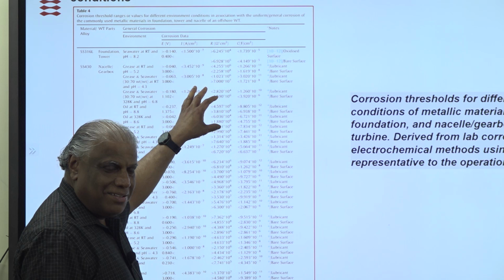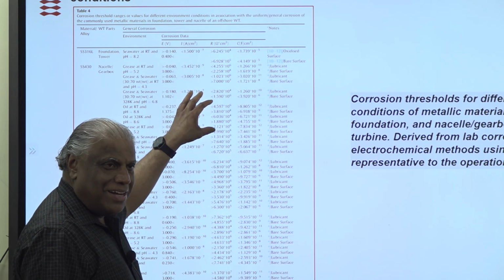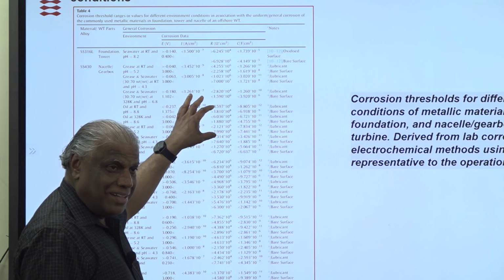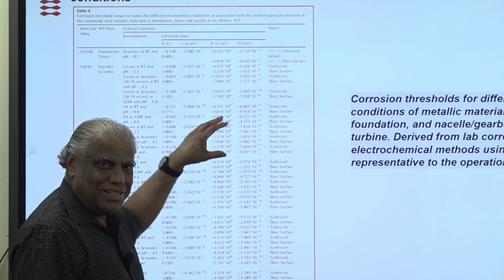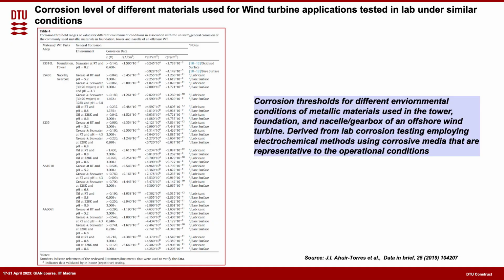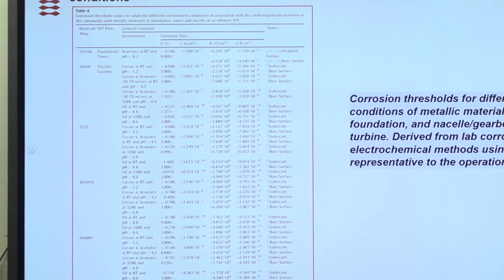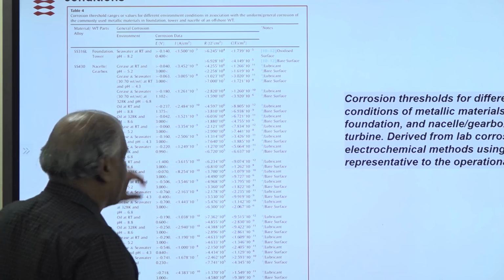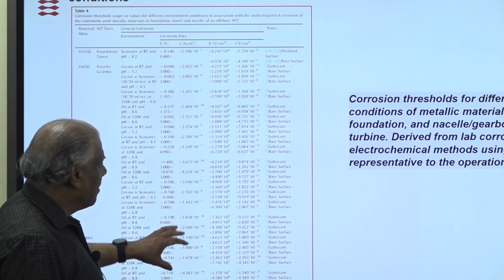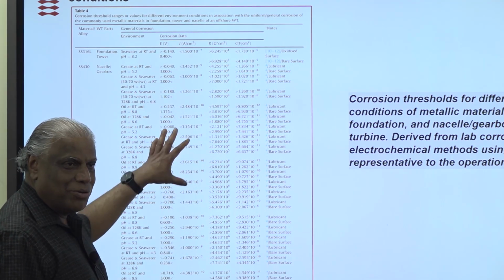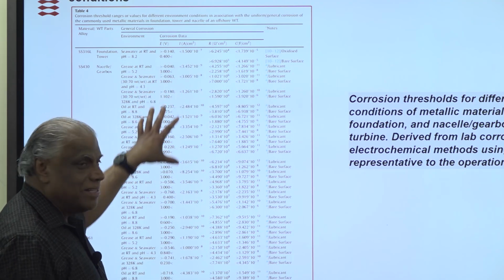So that they can get an idea about, if they use this material inside the nacelle, the gearbox, and the gearbox is having lubricant, so there are some materials that are corroding. That corroding environment will be lubricant mixed with water, and in that condition, what corrosion rate can they expect? And similarly, in some other places, when they have some other environment, what corrosion rate can they expect? Like that, they made this table.